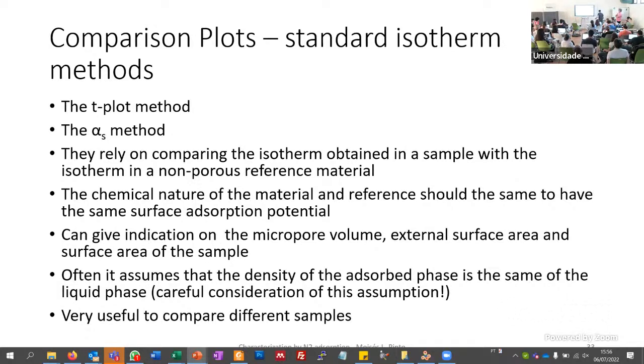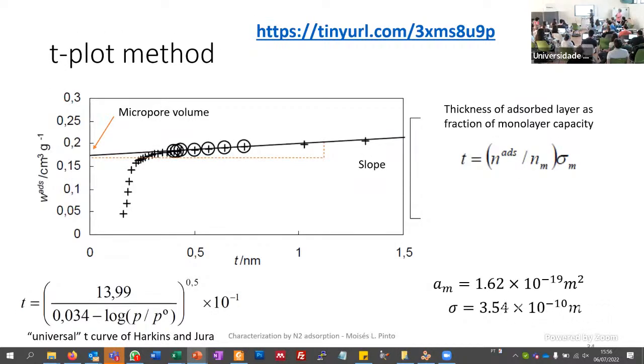And how can we use it? So the strategy here is a little bit different. What we need is, instead of adsorbed amount, we can transform this into adsorbed volume. If we know the molar volume of the liquid nitrogen, we can multiply the adsorbed amount by this value and obtain the volume of adsorbed nitrogen. So we can plot this volume, and here we plot the thickness of the layer that is adsorbed.